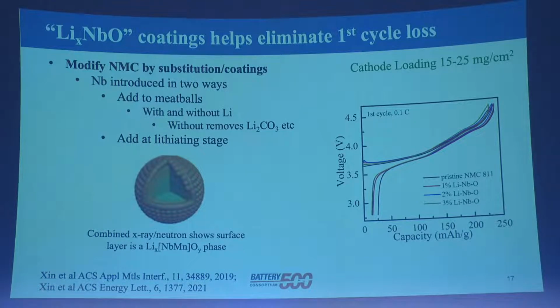And I should have said that the data we showed a few slides ago did not use a standard electrolyte. It did not use a graphitic carbon. It used pure lithium metal. So we had to learn how to plate lithium metal out. And what the researchers at Pacific Northwest National Lab, in fact, did, I'm not sure they did it knowingly at the time, they basically went back and used the old Exxon electrolyte that we used when we used lithium metal. So ether-based solvents, and they used LiFSI as the salt, which wasn't available back in those days. And that seems to plate lithium fairly effectively.